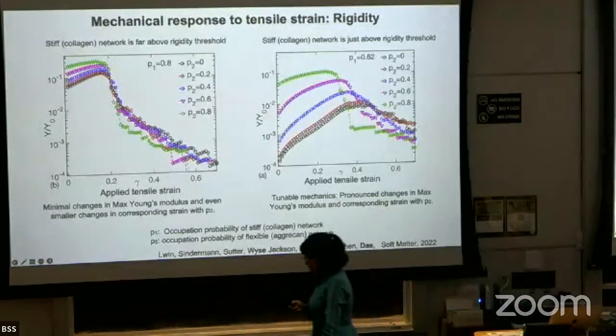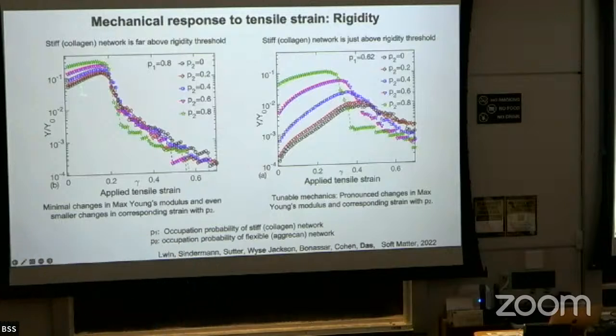Okay, so we look at two different cases. One case is when the collagen network is far above the rigidity threshold. So this is the situation when you're close to the bone, right? And we are looking at the normalized Young's modulus as a function of the applied strain. Initially, as you increase the strain, you will see a little bit of strain stiffening. But then it reaches a point where your bonds start to break, and so you see a softening, right? And for a collagen network that's super dense, these curves for different values of aggregate in the second network kind of lie on top of each other. There is some change, but not too much.